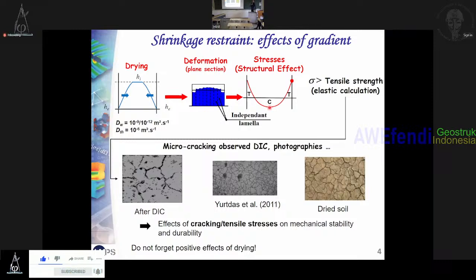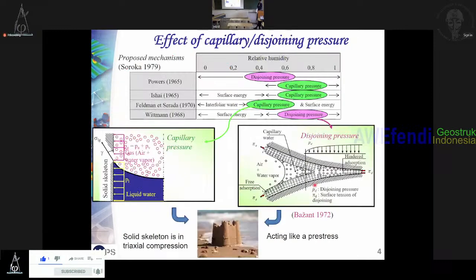And you know that tensile strength is quite low in concrete. So most of the time we have cracking, and cracking can be observed by eyes or also by digital image correlation. So we can say that this cracking at the surface will decrease the mechanical properties and will increase the transport properties. But do not forget that drying can be positive.